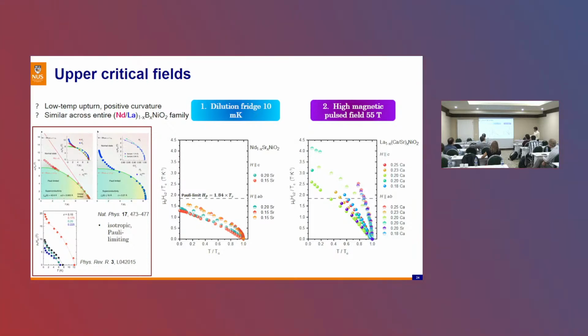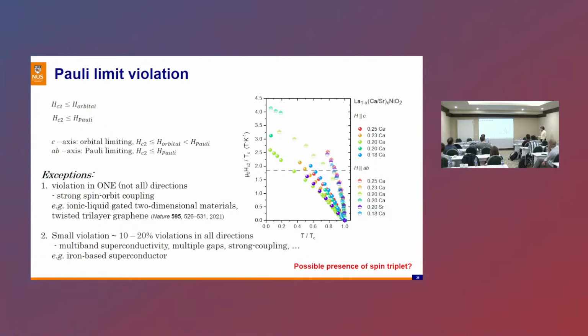So this violation of the Pauli limited behavior is really a tricky thing that we cannot really find reasons for right now. Because if we look at BCS, you might have these violations, but not in a way that's similar to what we have. For example, ideally you will have this Pauli limited behavior both in the case of in-plane and out-of-plane applied magnetic field. The out-of-plane magnetic field is probably related to the orbital effect, while in the case of the in-plane it can be because of the paramagnetic Pauli effect, okay? While in the case of this lanthanum nickelate, the violation is in all directions of the crystal axis.